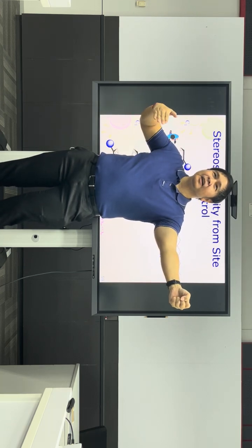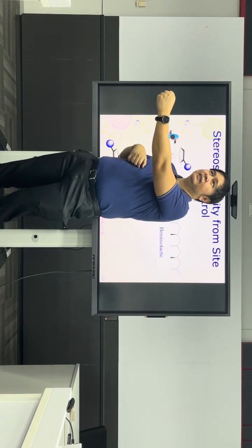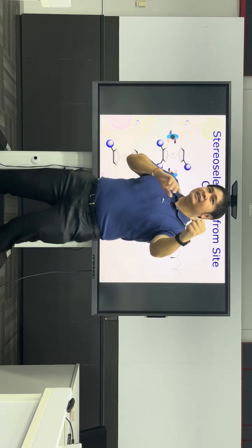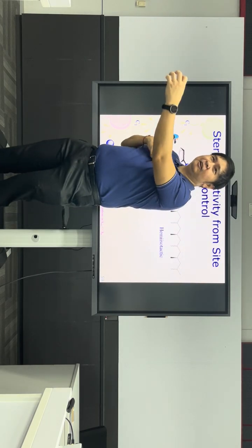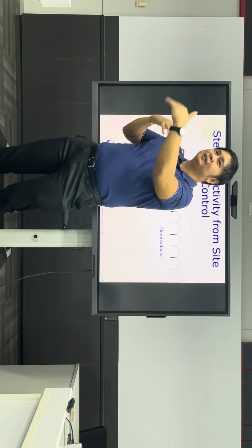What happens is, the polymer is here and this site is empty. But before the new monomer comes in, this R group just moves to the other side. This is called epimerization. Site epimerization: the site is epimerized, or moved to the other side. This happens, but in a small percentage. When that happens, you kind of screw up the whole thing, right?